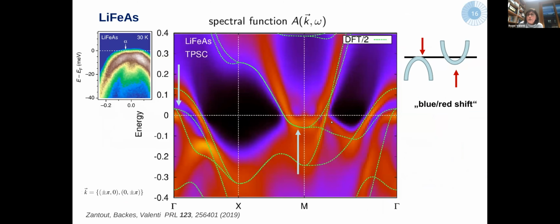So let's look now at this red-blue shift or blue-red shift, depending on where you define the blue and the red. How is this described by this type of approach? What I'm showing here is the band structure. The green lines are the DFT band structure for lithium iron arsenide, where I did a rescaling of 2 in order to compare the bands better. And the color mapping is the result of this DFT plus TPSC, where yellow means more intensity.